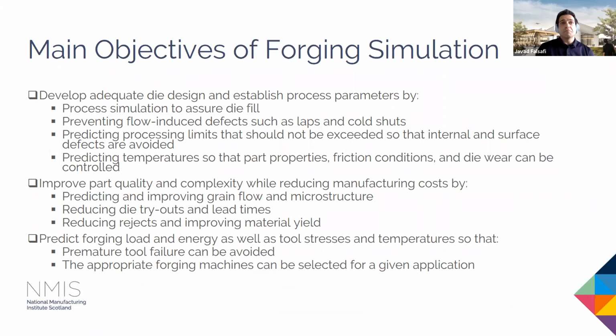So in terms of some of the main objectives of the process simulation, I've listed some in this slide and categorized them in 3 categories. First is adequate die design and establishing process parameters, which is about design of the forging sequence, the preform shape, prediction and improvement of flash dimensions and material yield, prediction and elimination of defects, faults, or fractures, and also investigating the effect of temperature and friction on metal flow. Second, at a more advanced level, improving part quality and complexity through prediction of microstructural features, prediction of elastic recovery, and residual stress that could potentially lead to part distortion and tolerance nonconformity. And last but not least, we've got prediction of forging load and energy, as well as tool stresses and tool life.